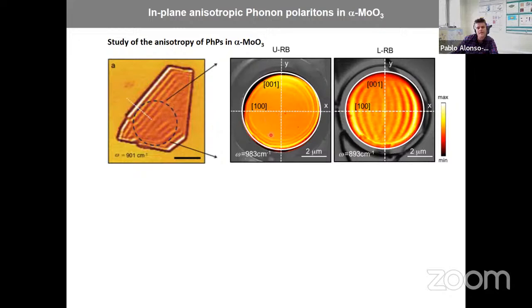The polaritons propagate in the material, and, I didn't explain this, but the SNOM tip works like an echo detector. So it launches the polaritons in one position, but it measures also at that position. So it measures what is coming back. It's like a radar. So if you want to probe all directions in the material, you can make a disk, and then you put your tip here. For example, it launches, they go to the edge and then come back, but they go to all edges, right? They go to all directions in the disk, and then you can see if they propagate in all of them.